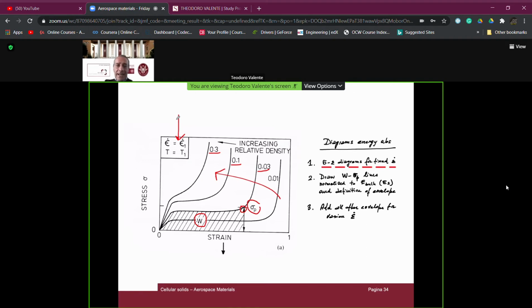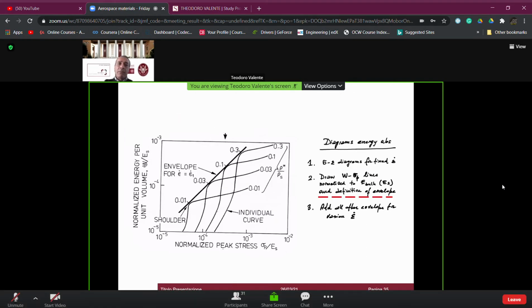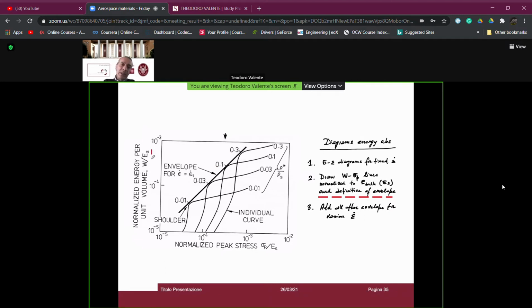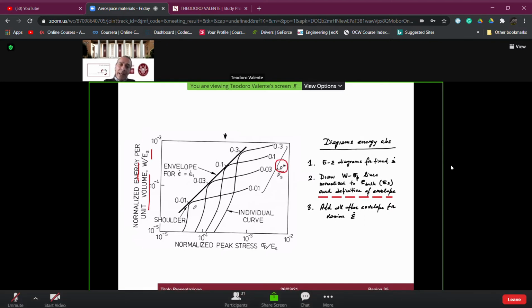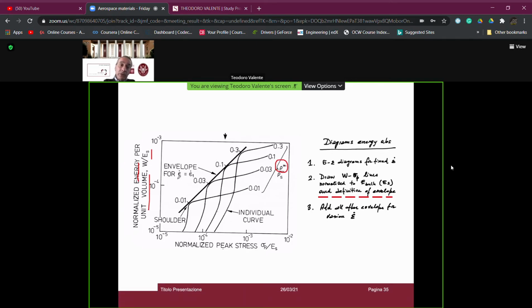After having made this at a fixed value of the strain rate, we can define another diagram in which we report, for simplicity, normalized by the Young modulus of the corresponding bulk material, the absorbed energy per unit volume, that is the area, this area, in terms of the corresponding peak stress, for a given value of the mass density of the cellular foams. And then we do have a maximum for each of these conditions for a given value of the strain rate, and we can